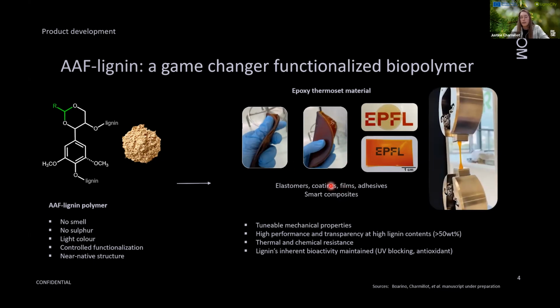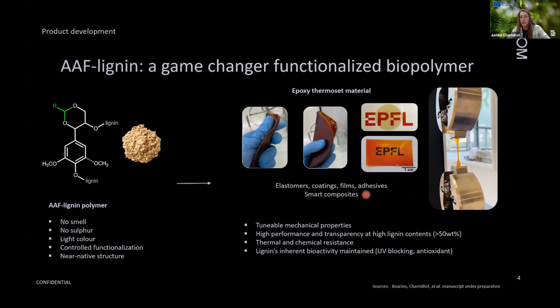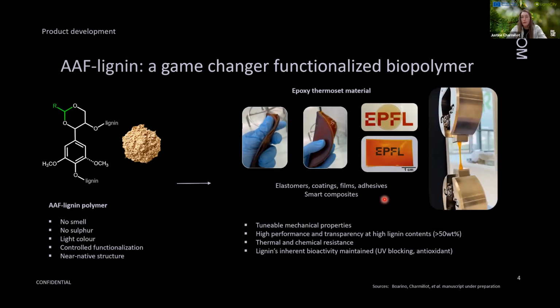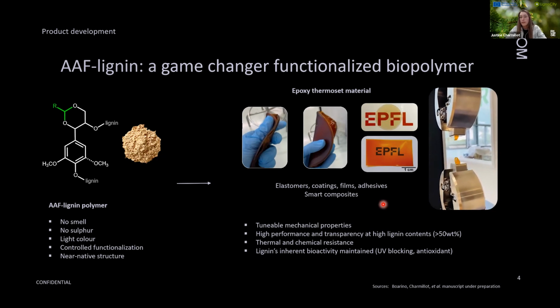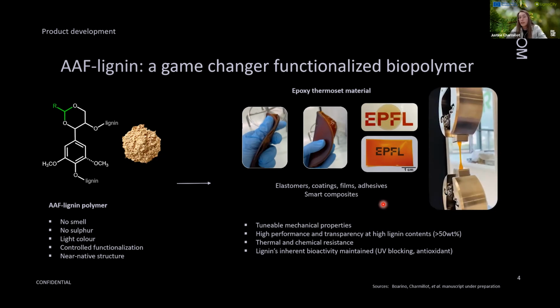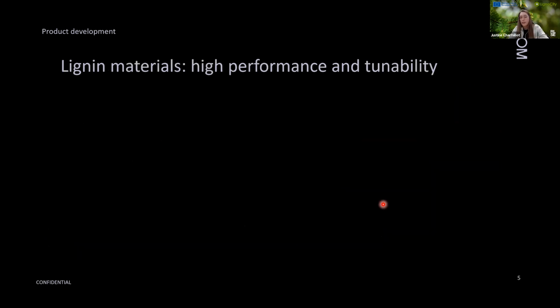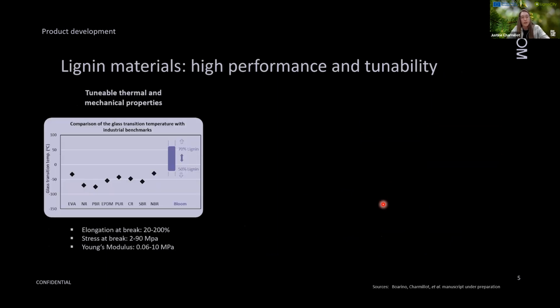And what we can see is that we can actually tune the properties, because we can vary the lignin content, and even at really high lignin content, more than 50 weight %, we still have a good transparency and good performance. So they are not brittle. They are also thermally and chemically resistant, and we focused on also measuring the non-lignin properties, such as the UV blocking and the antioxidant character of those materials. So here I can show you such examples.